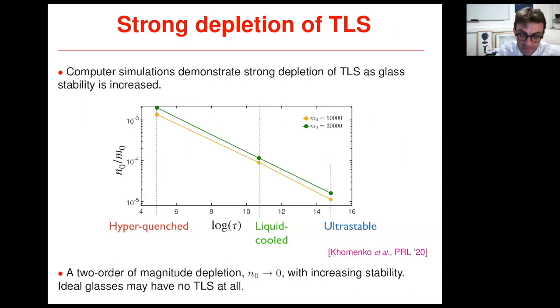So what I'm showing, and this is almost my last slide. We have used, again, computer simulations using the swap Monte Carlo algorithm to address this question in simple models in the computer. So we have been able to directly estimate in this model how the density of tunneling two-level systems is changing by changing the stability of the glass from very stable to poorly annealed systems. And this is the main result of this analysis. We find a very strong reduction in the density of two-level systems by about 100, a factor 10 to the 2. So 2 orders of magnitude depletion of the total number of these two-level systems in the glass as we go towards more stable systems, towards this vapor deposited system.